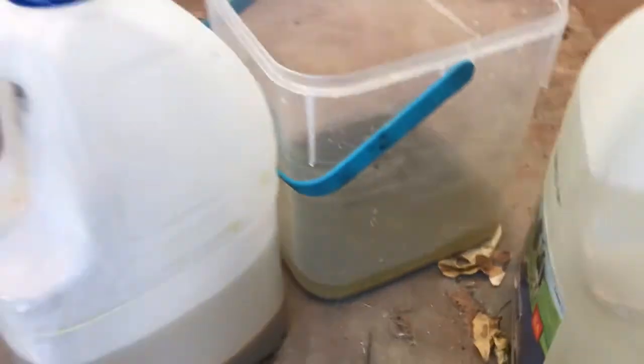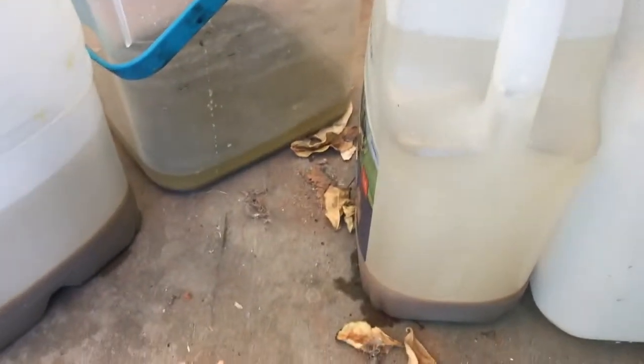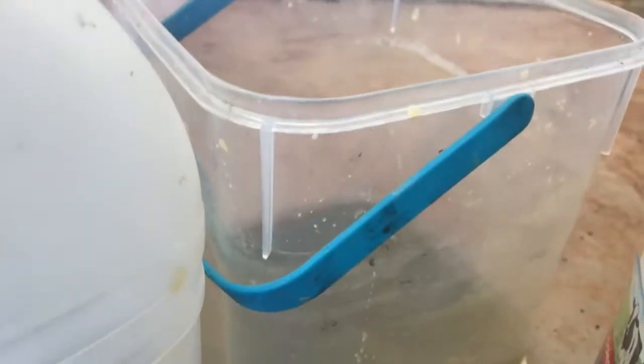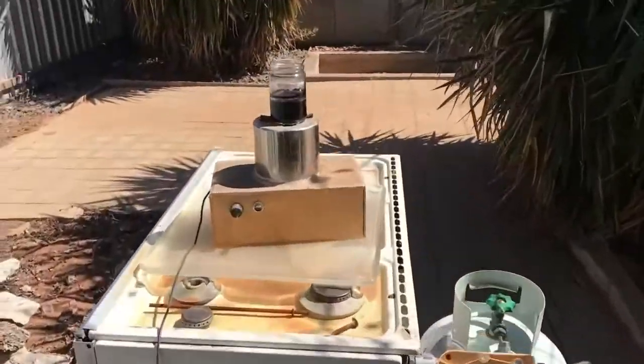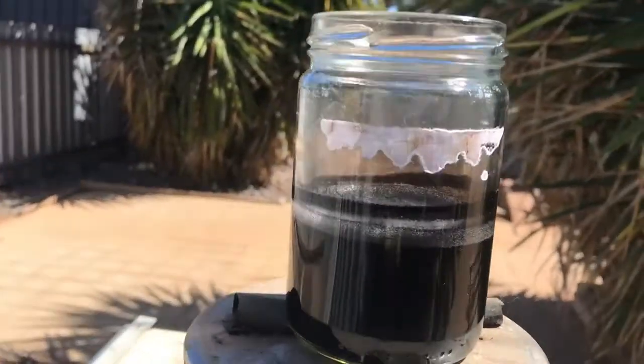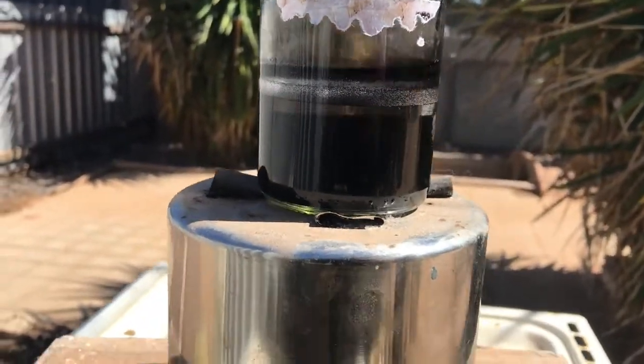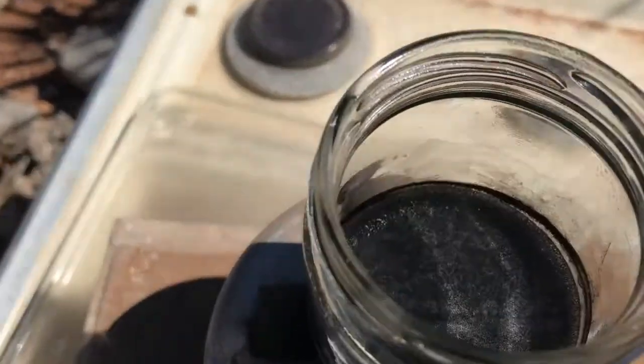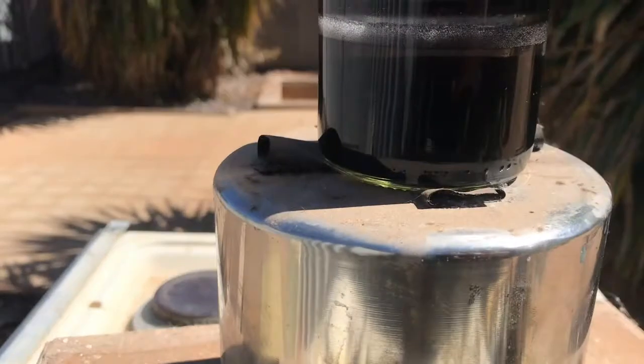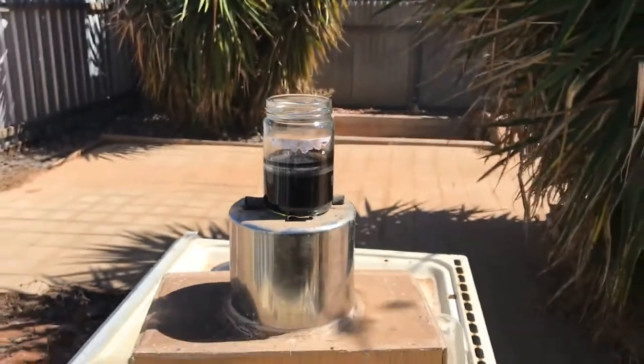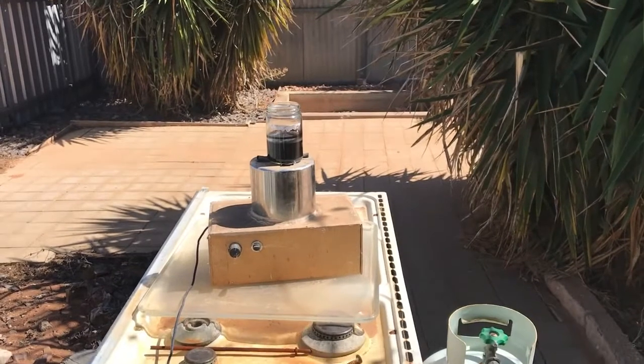But what I was doing, I grabbed a bit of that after it's been washed like 3 times. I filled that bucket up with water. I only used tap water this time because I didn't want to waste it because it was contaminated. Nothing seemed to be happening. I've got it right down the back here. I stirred it for an hour. I put some bleach in there and I came out and it was like, wow, it's turned black. So that might be nickel oxyhydroxide, but a contaminated version of it.